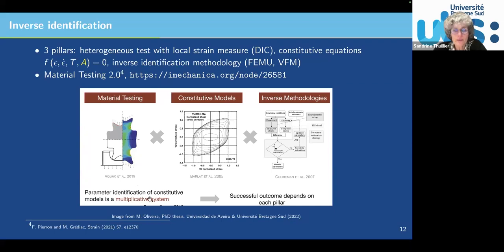So we can see this procedure as a multiplicative system, meaning that each pillar should be well controlled: the quality of the experiments and the quality of your DIC measure, the capability of your mechanical model to reproduce the mechanical behavior of the material, and the convergence of your inverse methodology. Each of the pillars is very important in order to reach a successful outcome.